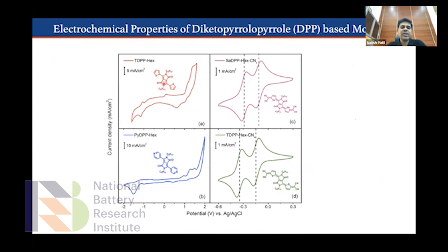For example, thiophene DPP does not really give a very reversible cycle, and pyridine DPP gives some sort of oxidation, but they are also not very stable and reversible. However, when you go to the nitrile, we clearly see a beautiful two peaks which are reversible in nature. For example, when you go to selenium DPP nitrile as well as this thiophene nitrile, we do see a very nice reversible peak coming in.